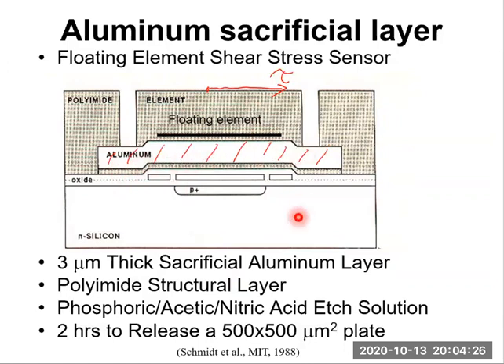Then this aluminum layer is removed by aluminum etching. This is a phosphoric acid plus acetic acid plus nitric acid. This is actually aluminum etching. It takes 2 hours to release a 500 micron by 500 micron plate. After sacrificial layer etching, this floating element is free, is freestanding, or is floating.